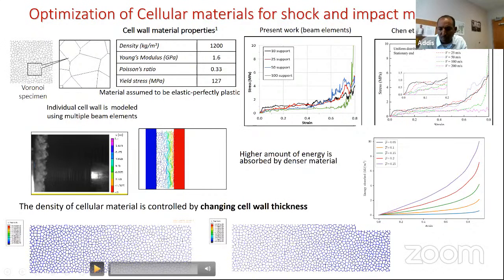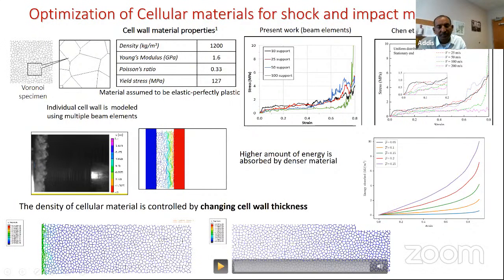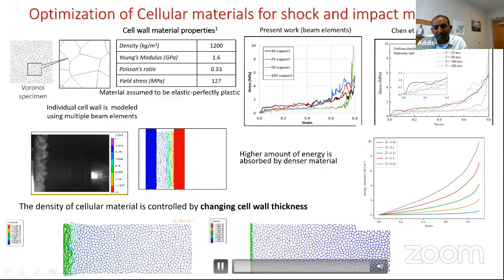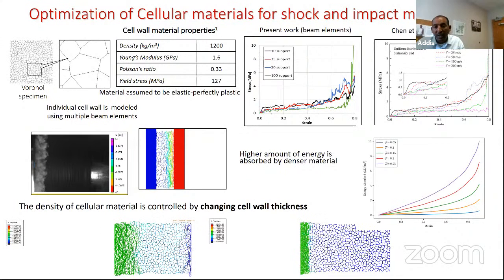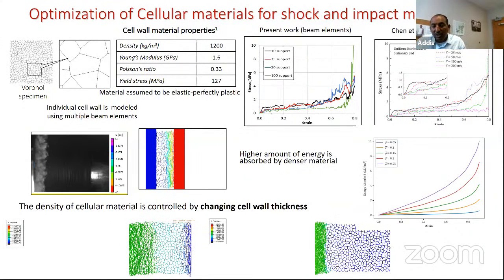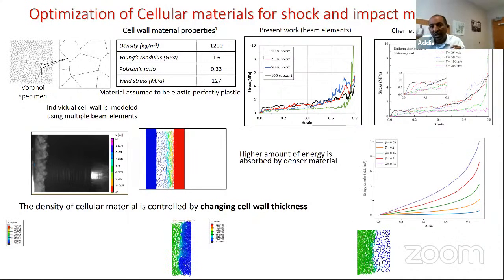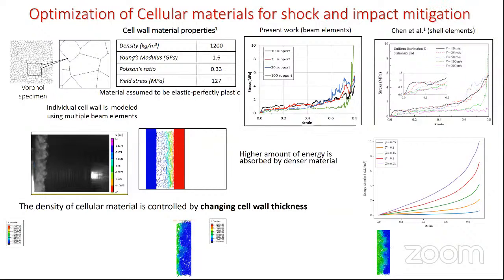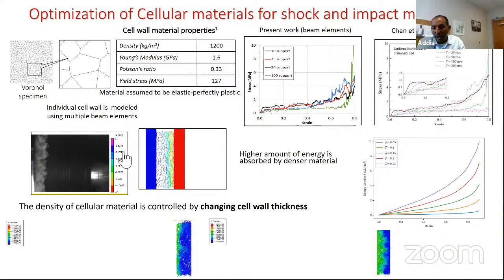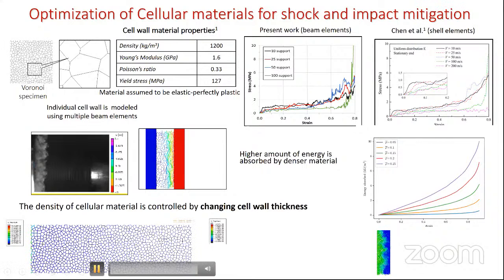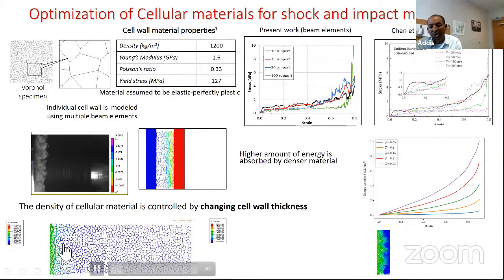These are our models that show where the materials are under impact when the different cellular materials are being used. In this case, for example, we use two material configurations. One is stiff cellular material. The other one is a more compliant or softer material. So the material response is graded from one direction to the other, and we subjected load in different directions. On the left side, you can see that the rigid side has been impacted, and the deformation happened, as well as on the right side.